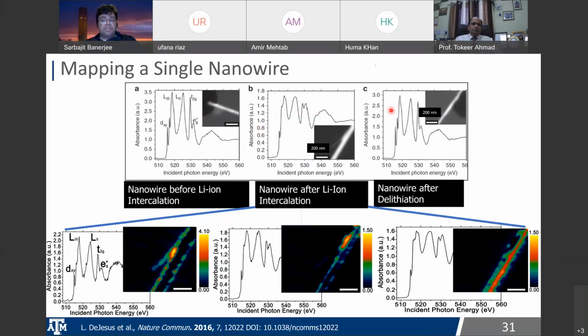And then when we pull the lithium out, okay, we kind of go back to the same thing that we saw before. The dxy state is restored because we've oxidized the vanadium back to V5+, and then again you can see here the t2g to eg star ratio has recovered, right? But if we take this middle, the lithiated version, and we map it, we actually found three entirely different signatures, right? This corresponds to a relatively low degree of lithiation. This corresponds to a medium degree of lithiation.